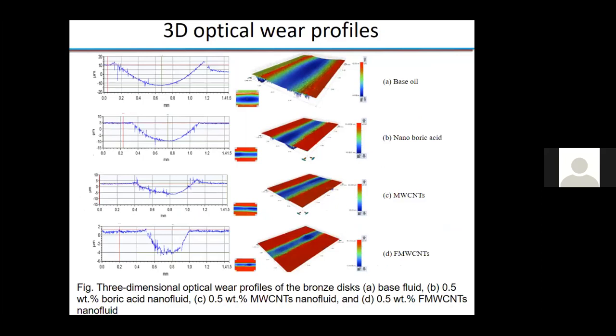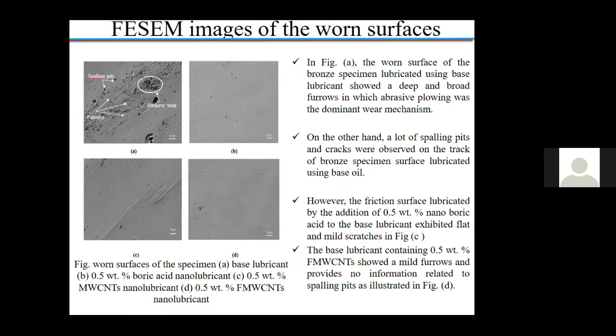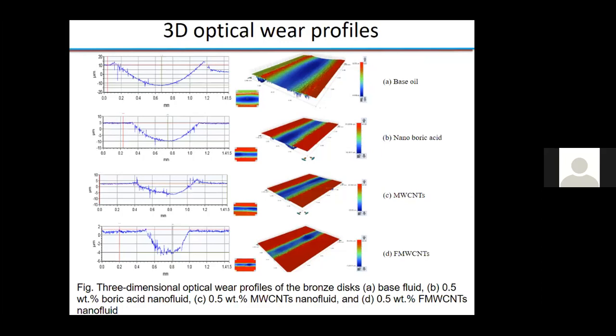To justify the applications of functionalized nanoparticles and other nanoparticles, 3D optical wear profiles were also analyzed and measured. So you can see a significant reduction in depth as well as width of wear in the case of functionalized multi-wall carbon nanotubes. Okay, so 2D diagrams and 3D diagrams you can see here. So this is how the nanoparticles minimize the friction and wear in the case of rolling and sliding contact surfaces.